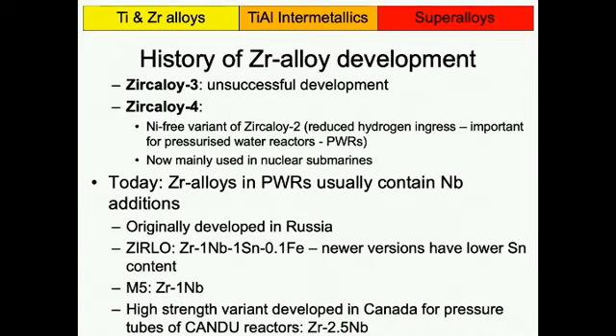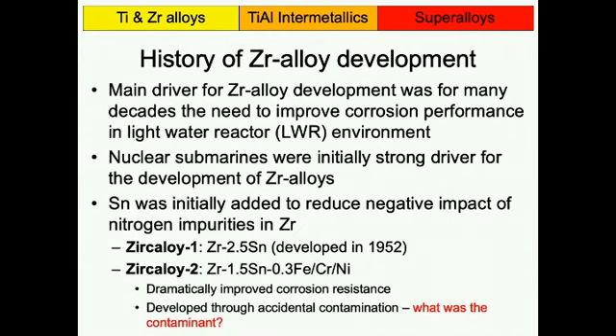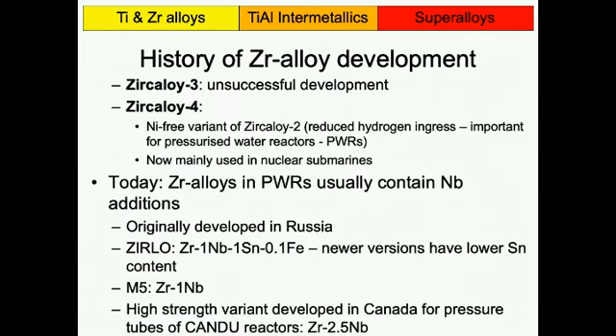Zircaloy 4 was then the next iteration, and it's essentially, in simple terms, Zircaloy 2 without nickel. So you can see here small amounts of nickel. There's a bit of nickel in there. The nickel was taken out, and it's essentially a nickel-free variant of Zircaloy 2, and it reduces the hydrogen ingress in this material.